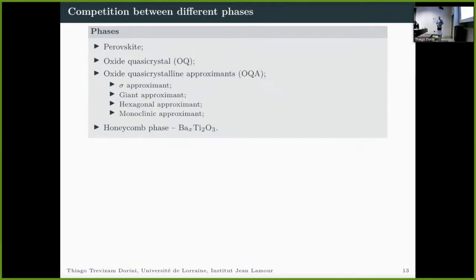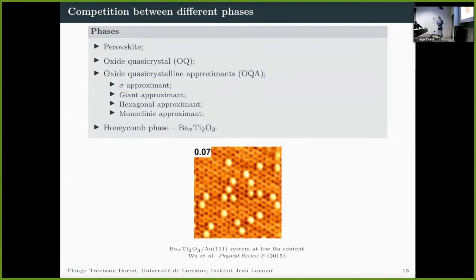I'd like to highlight that we have seen that we have the perovskite structure in these phases. We have the oxide quasi-crystal. We have a competition between these phases and also many other approximant phases. I've shown only one, but there is also a giant approximant, a hexagonal, a monoclinic, and some other approximant phases that have been discovered. In addition, for lower contents of barium, there is also a honeycomb phase that can be formed. Here we have an STM image in which you can see the hexagonal honeycomb structure of the titanium oxygen lattice, where barium is located in the vacancies of this lattice.